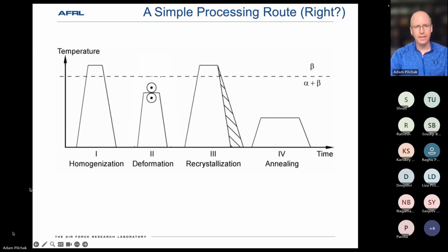And so for the Beta-Annealed condition, typically one would actually do the forging process in the alpha-beta phase field in step 2 here. And then once that's done and cools down, it goes into another furnace where it's taken above the beta transus for a period of time and cooled as quickly as possible, generally to try to balance the colony size.